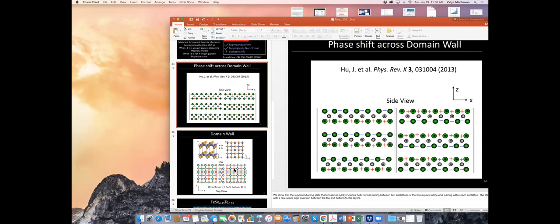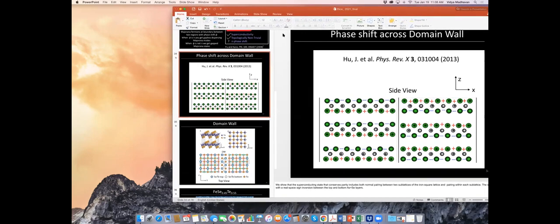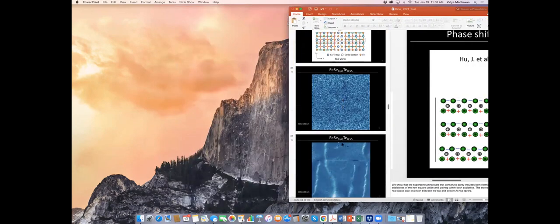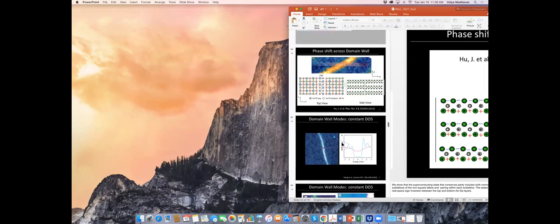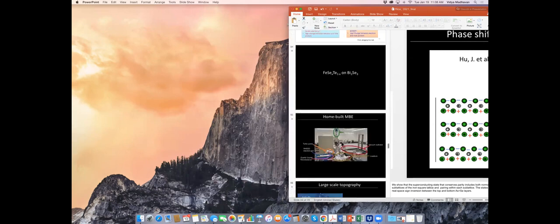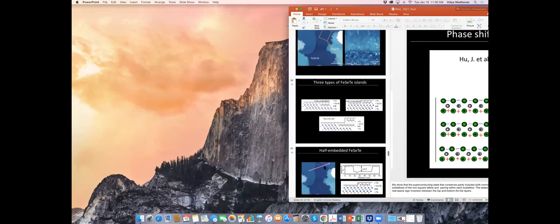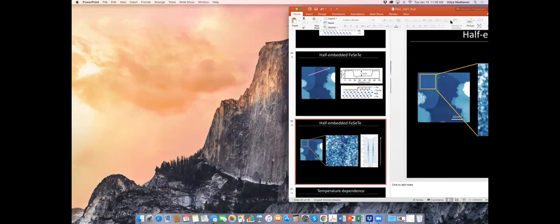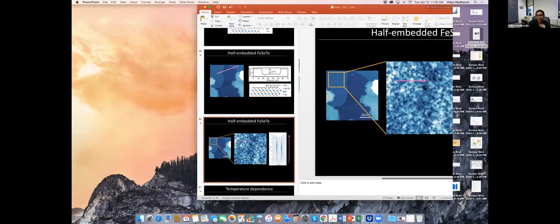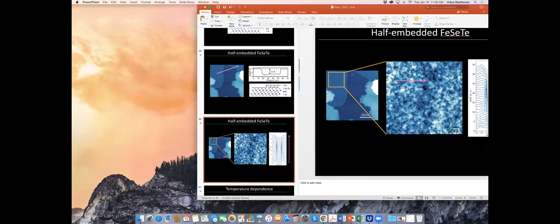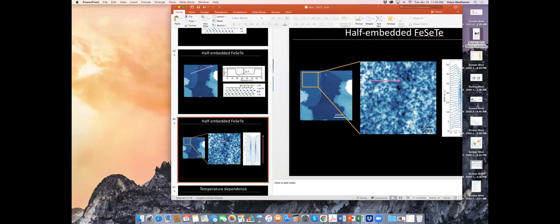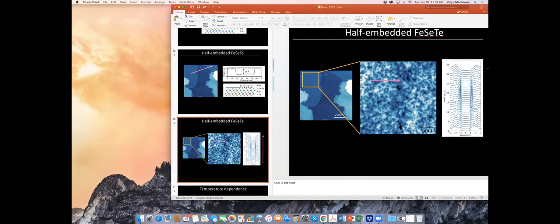I have a question regarding the growth of this iron selenium tellurium 50/50. You said that you can grow these materials without interstitials or iron excess. I find it a bit strange because that material actually allows iron excess in the lattice, and normally people anneal the samples, and still if you anneal it, it's not guaranteed that it's not 100% free of the excess of iron. You're absolutely right. So I'm puzzled by that, also from the phase diagram point of view, it's a little bit surprising to me that one can access it.